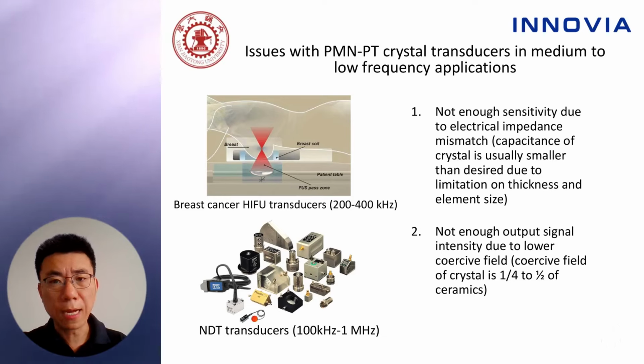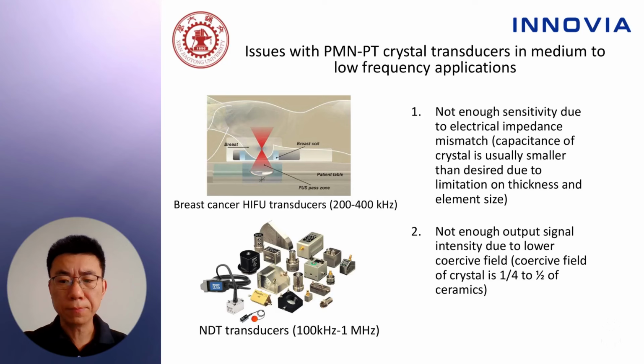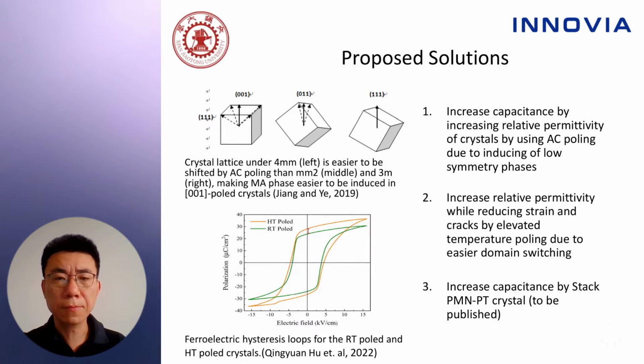Secondly, not enough output signal intensity due to lower coercive field. The coercive field of PMN-PT crystal is usually a quarter to half of that of PZT ceramics. What are the proposed solutions? Firstly, we propose increasing capacitance by increasing relative permittivities.